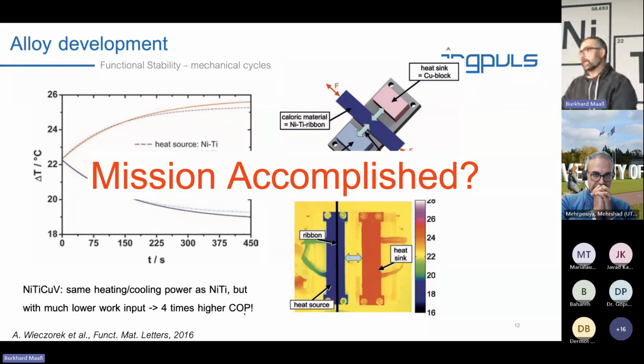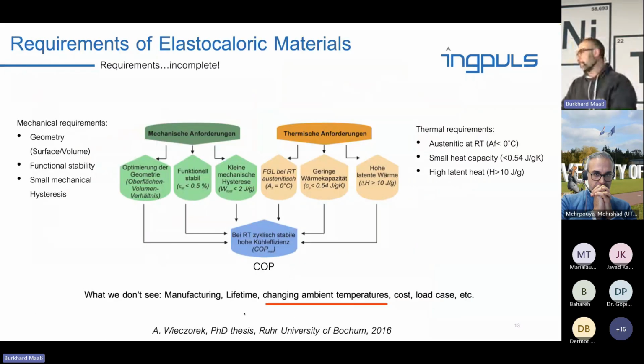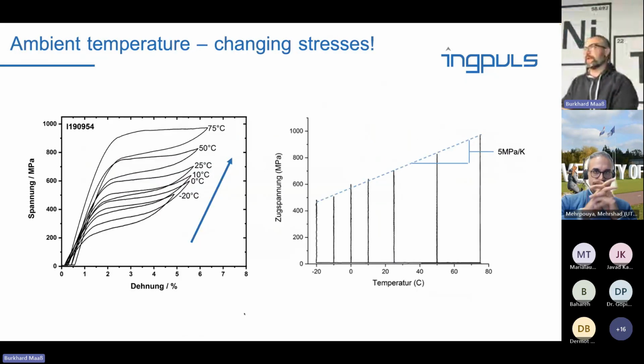Of course not, because now somebody comes and says, I want to put this in a car, and my car goes from Alaska to Arizona, and what about the temperature changes? There's not much use in having something pseudoelastic at room temperature. And for those who know this, Nitinol is very nasty when you change temperatures because it changes its mechanical properties. We call this the Clausius-Clapeyron effect.